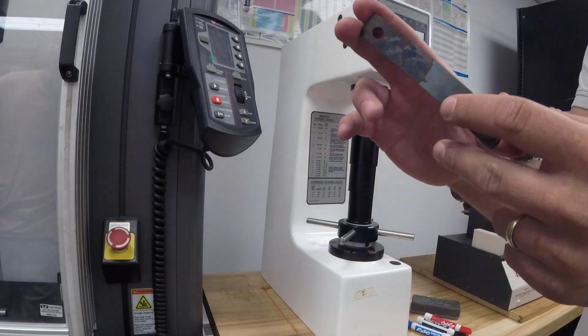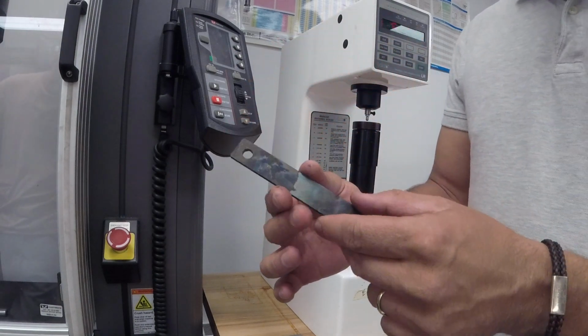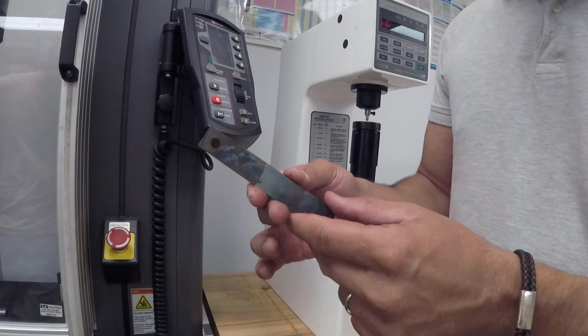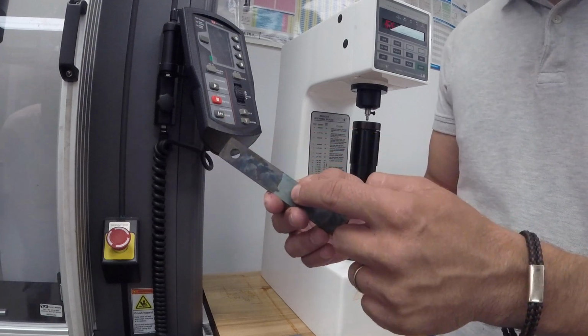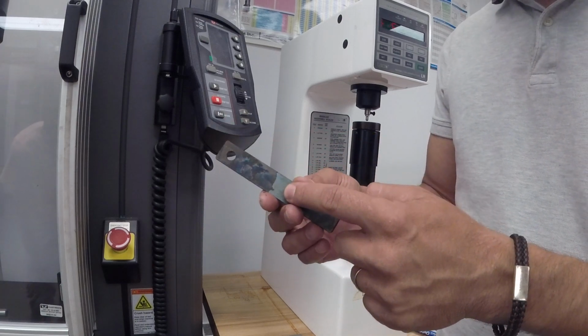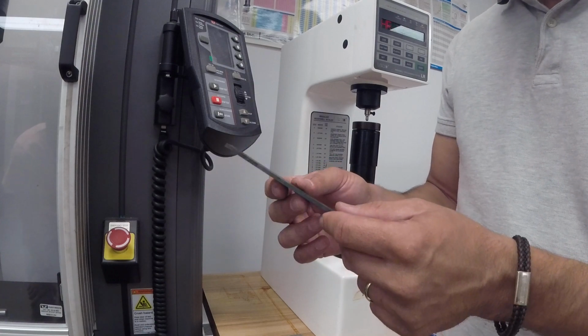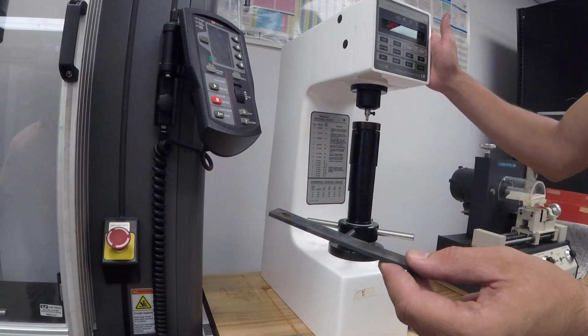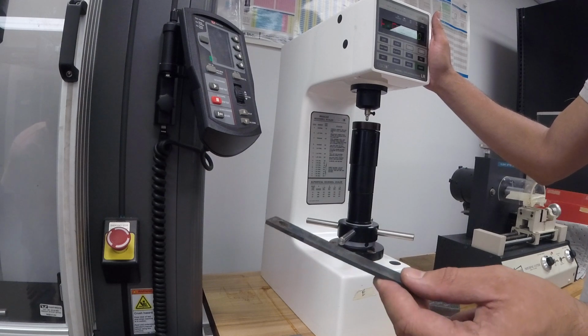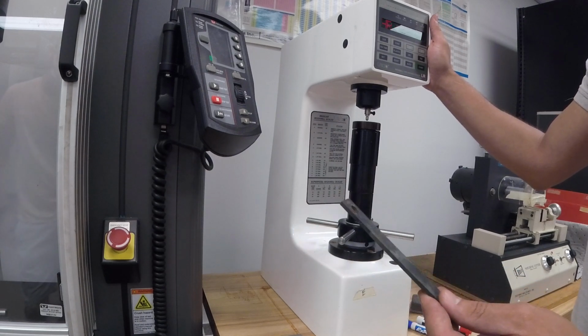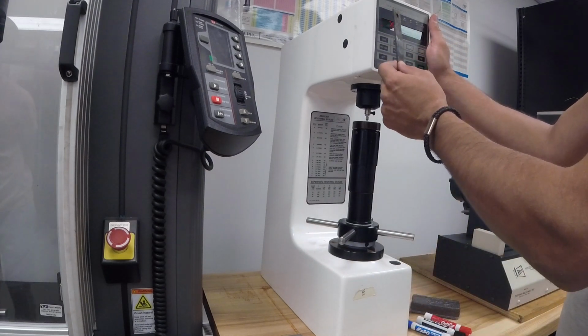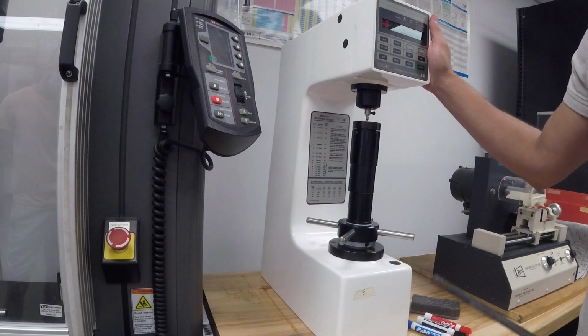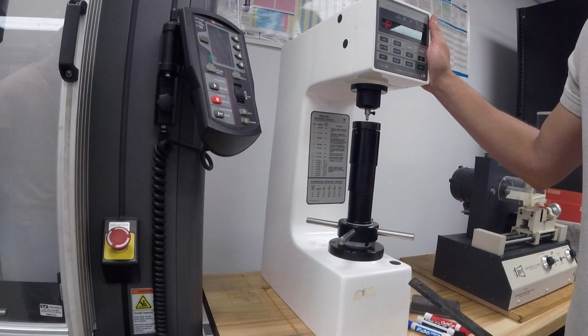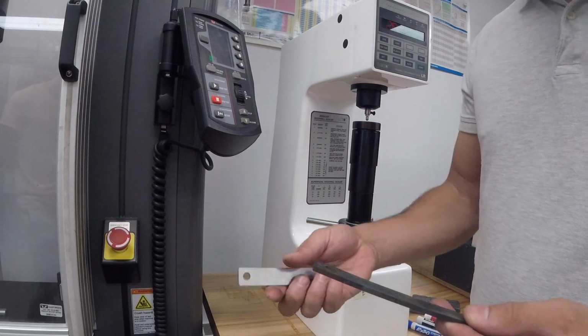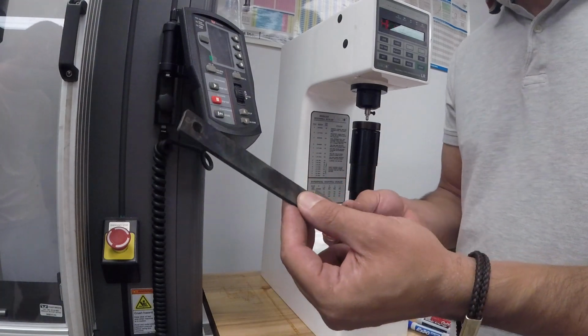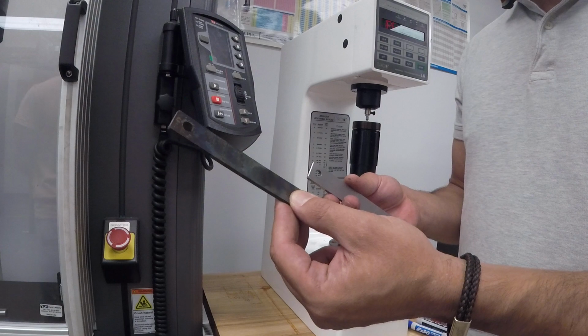Okay, so why this happened? Because we increased the hardness, but the toughness decreased in this one because of residual stresses we have. As you can see, this machine shows us the hardness. So based on the hardness for the same method, HRB, increased 30 unit approximately. For this one was around 90. And we get around 120 for this one. Means this increased that 30.